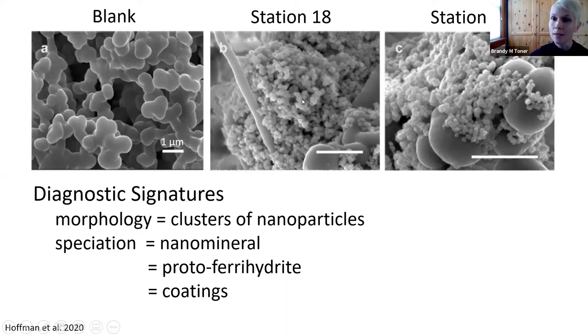that's right. It's an example. I mean, it was ubiquitous. Everywhere on the filter, we had these large clusters, large meaning several micron in diameter, clusters of nanoparticles. These are the iron 3 oxyhydroxides from which the XAFS that I showed you come from. And we can track that morphology off axis, and we can also track the speciation of the material.